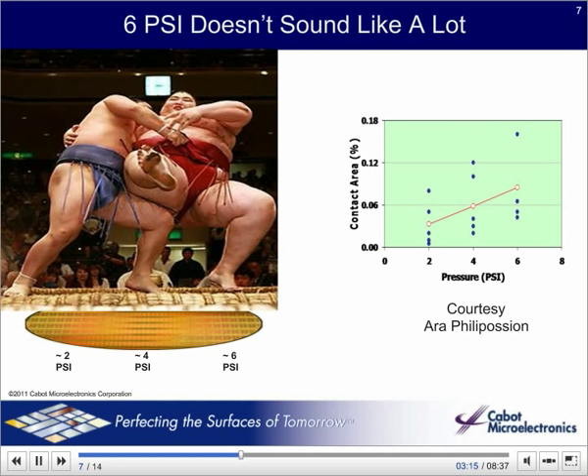As I mentioned, the asperities are really what contact the wafer. They represent about 0.1% of the total wafer area. So if a process runs at, say, 2 or 4 or 6 pounds per square inch, that might not seem like much. But if only 0.1% of the pad is making contact, this is really a force of 6000 pounds per square inch. Imagine one 300-pound sumo wrestler lifting a second sumo wrestler over his head and standing on one toe. That's heavy. No wonder we get some scratches from time to time.